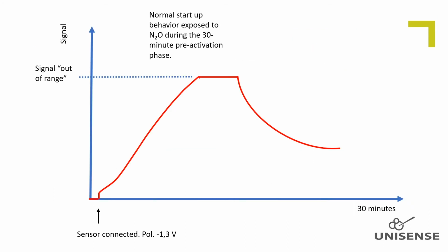The indium working electrode reduces nitrous oxide efficiently in the organic electrolyte, but only if the surface is reduced. A layer of indium oxide is formed when the working electrode is not negatively polarized. This layer makes the working electrode completely inactive to nitrous oxide reduction. Therefore, this oxide layer must be removed in an initial activation process. This is done by applying a high negative polarization for about 30 minutes, which reduces the indium surface.